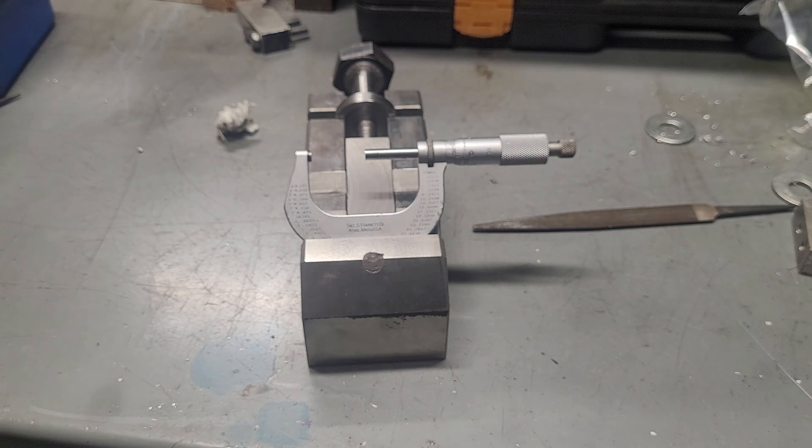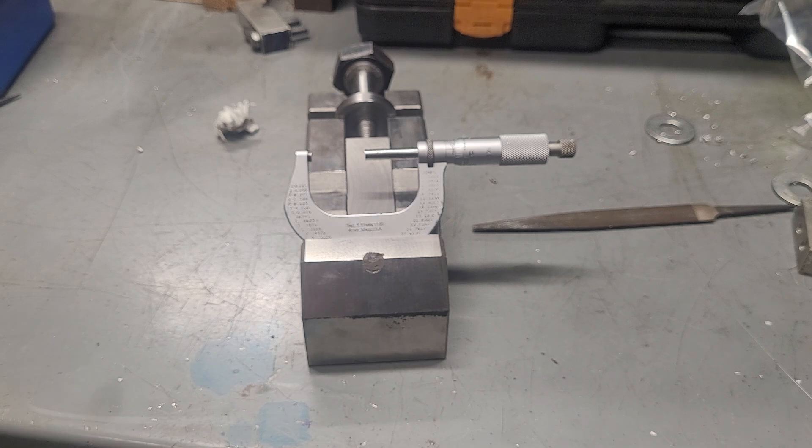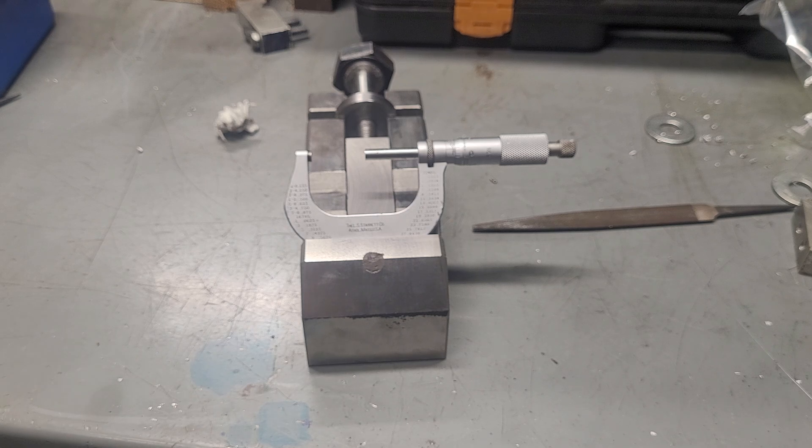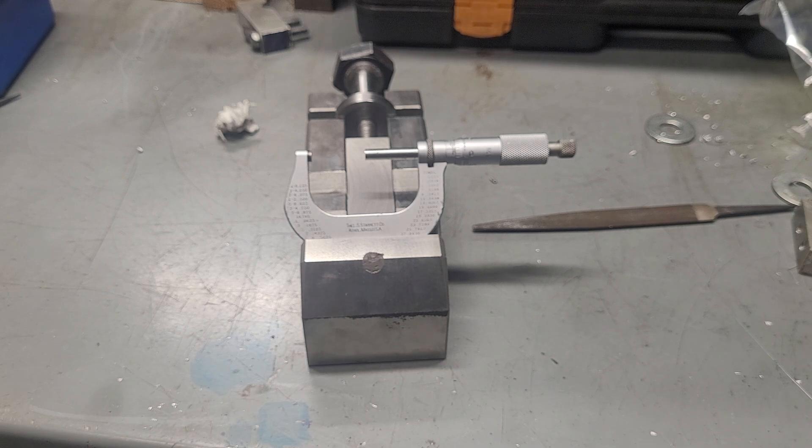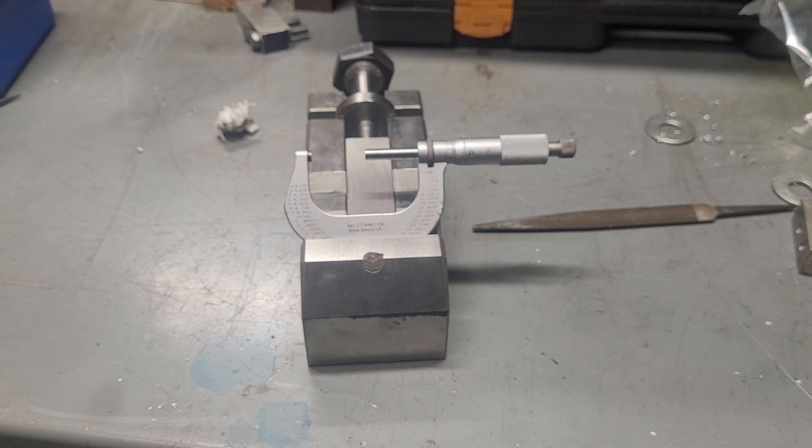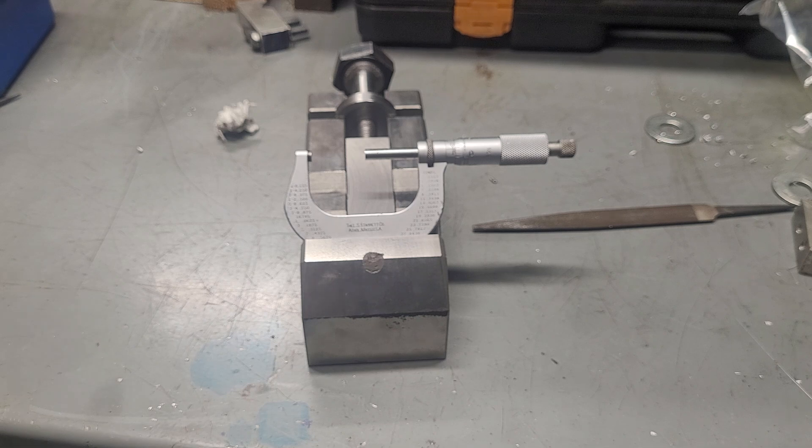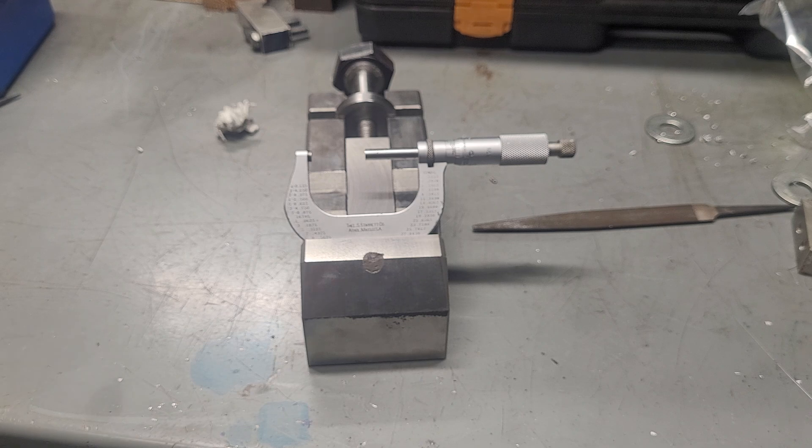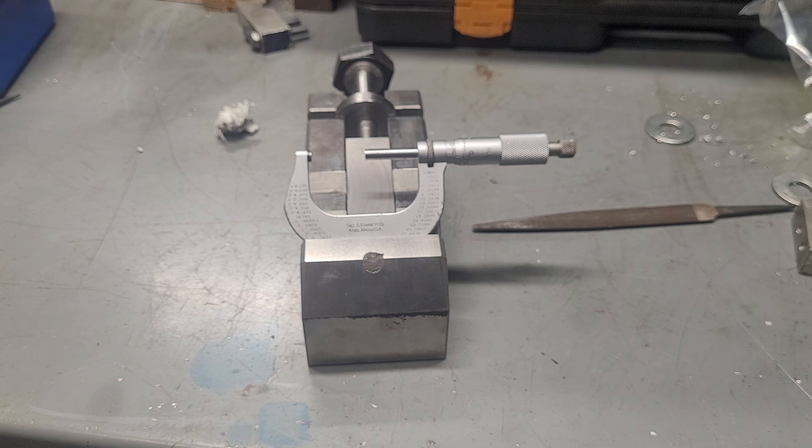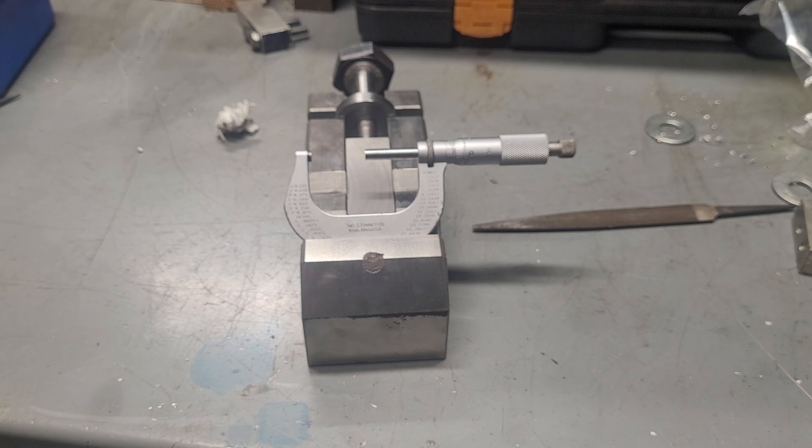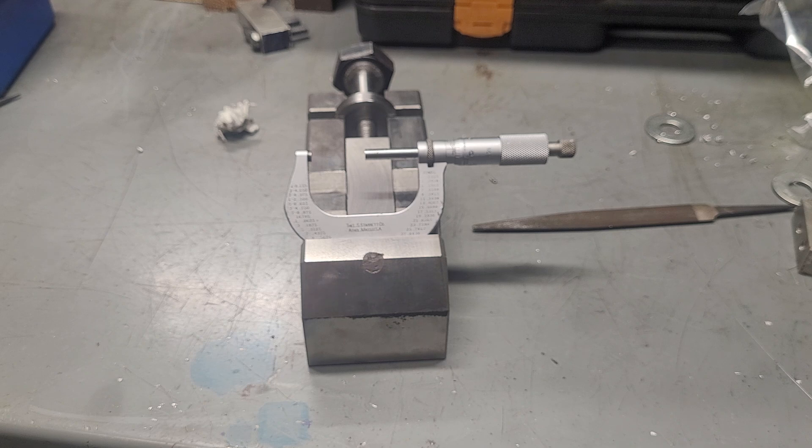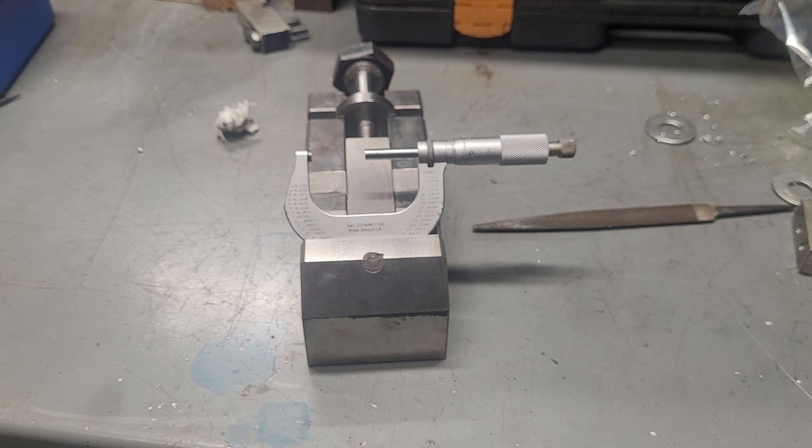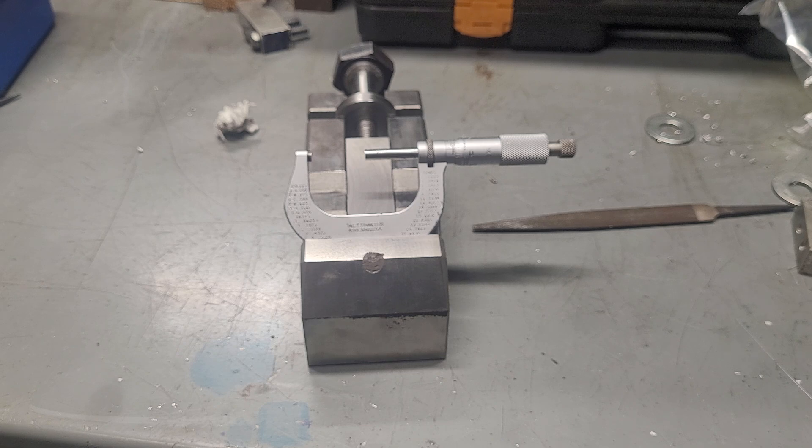So, you know, this is just fun. It's really, I think, good to demonstrate these type of lessons to people because it's not something you might necessarily think of mattering. And the larger your parts, actually, the more heat matters. What I've learned is when you get to, you know, like two, three, four inch shafts on a lathe, you really need to pay attention to your heat. What I actually had started doing, and still do this, is I'll walk away from my finish pass. Walk away, leave it for an hour, let the temperature stabilize, and remeasure it. Because I could not figure out for the life of me why I kept having oversized parts I was measuring on the machines. And I had failed to take into account thermal expansion.